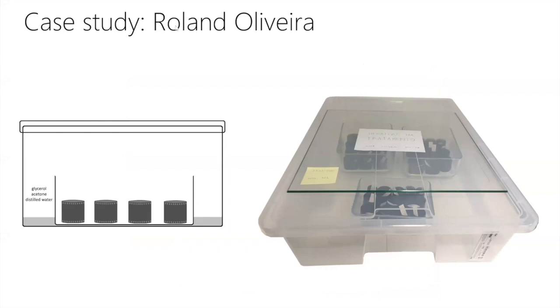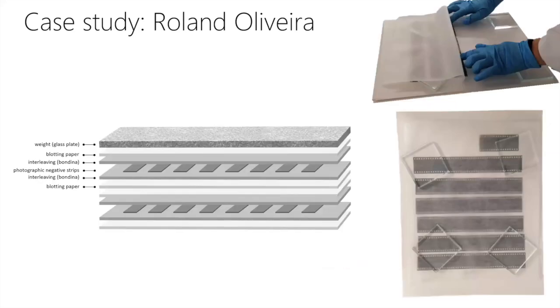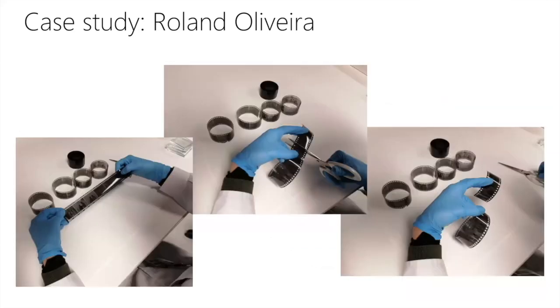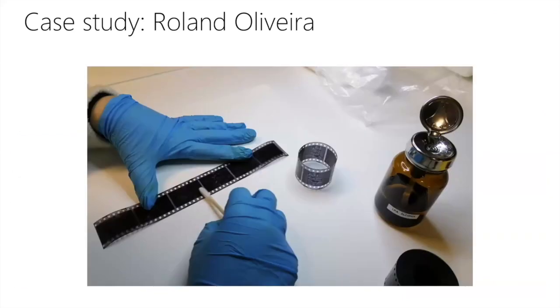The developed procedure was based on the de-shrinking process that was adapted from the conservation of motion picture film literature, using a chamber with vapors of glycerol, acetone, and water combined with the flattening under weights of the films. Before treatment, each roll was cut in strips of 6 frames with scissors. Superficial dirt and debris were gently removed from the strips using an air bulb. The strips were then cleaned on both sides using ethanol applied with a cotton swab to remove the fungi.